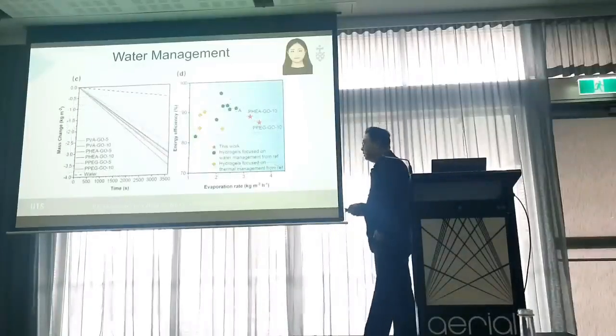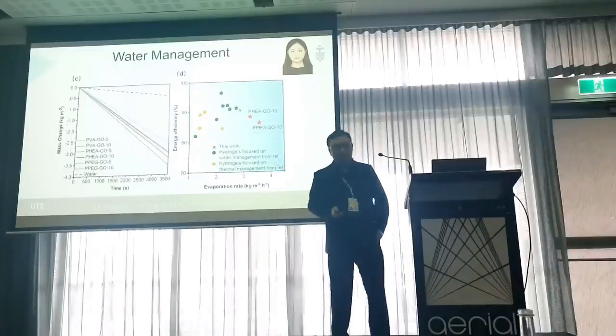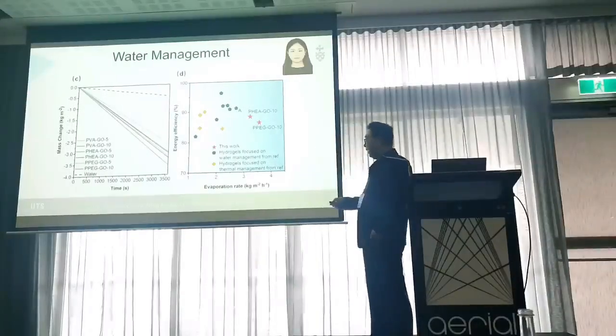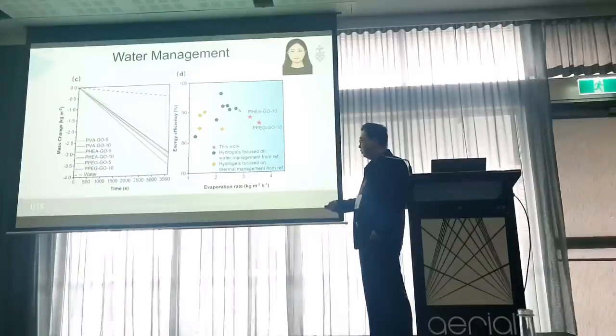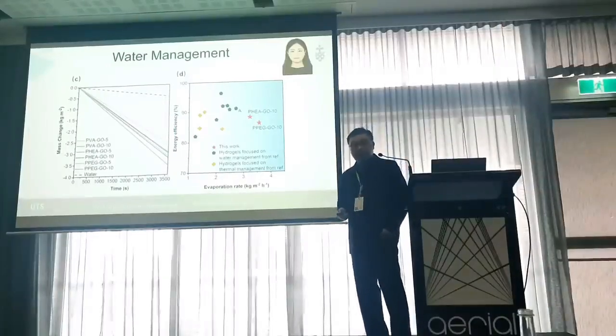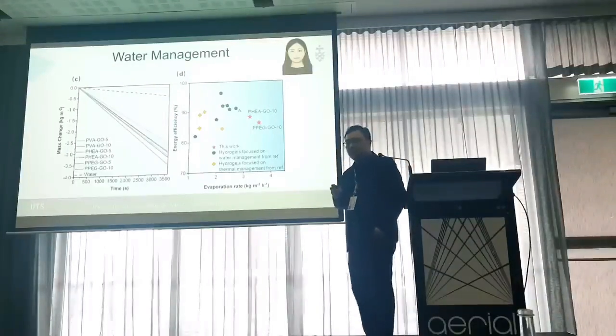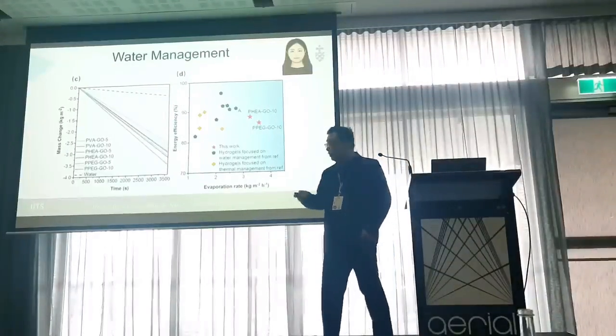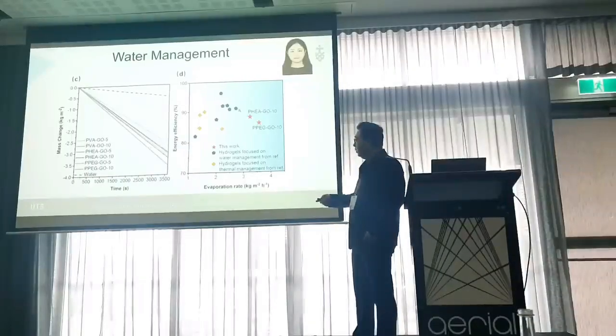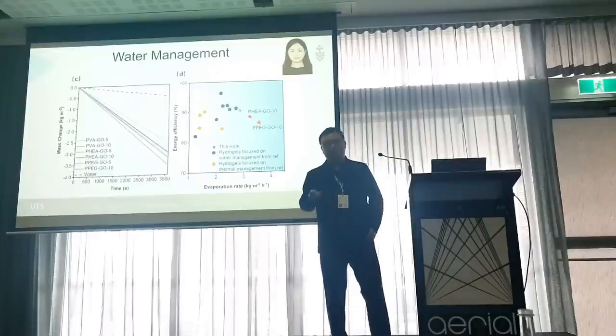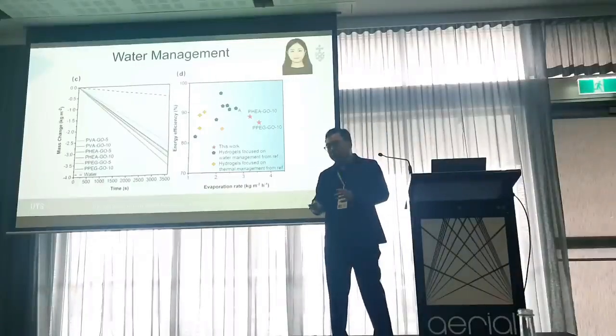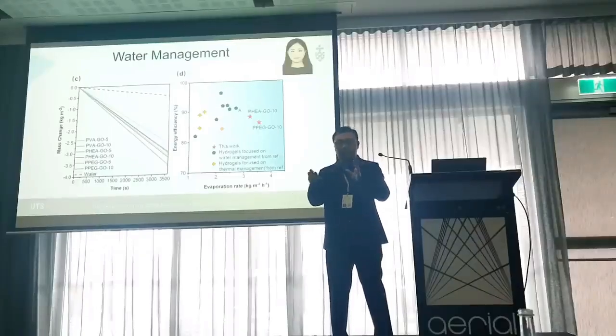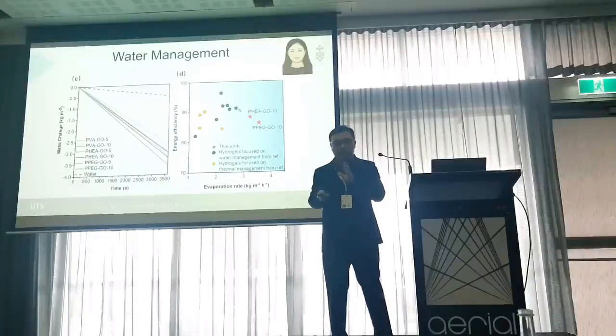So then we test the water evaporation performance of all these hydrogels. As expected, the PEG hydrogels with graphene oxide as the photothermal material show the highest water evaporation rate. They achieve 3.6 kilograms per square meter per hour, and this value is definitely higher than the PVA one, which is about 2.8 kilograms per square meter per hour. So it demonstrates that the rapid water transport definitely affects the SVG performance.